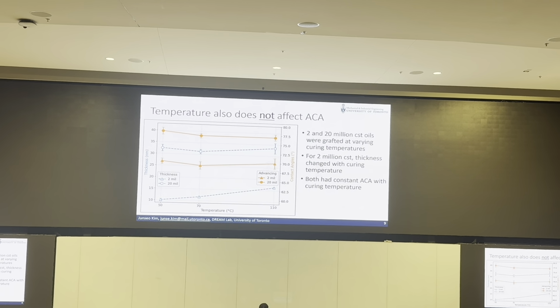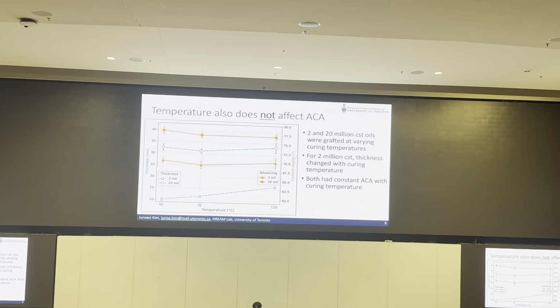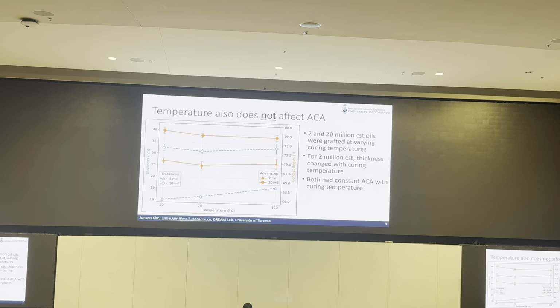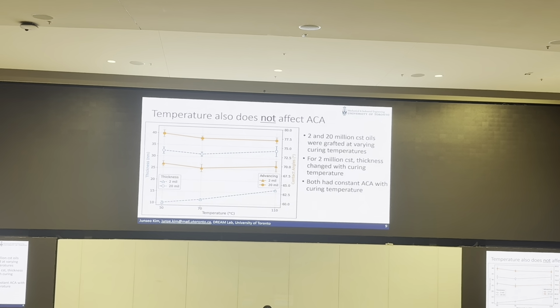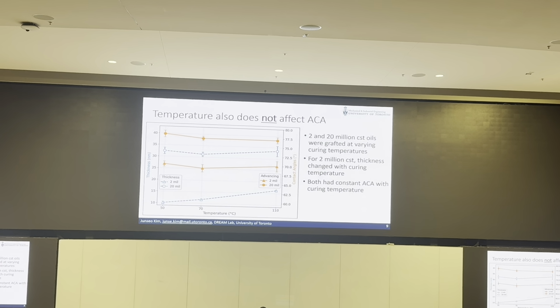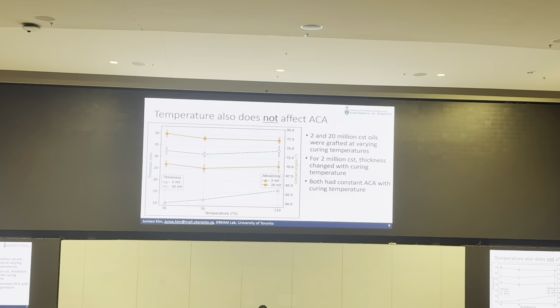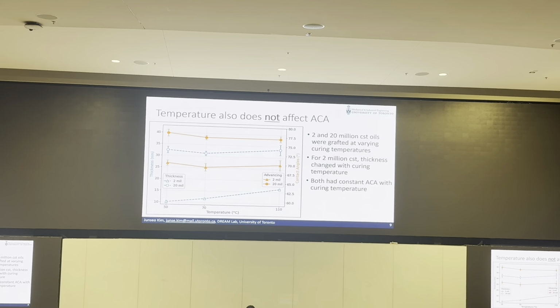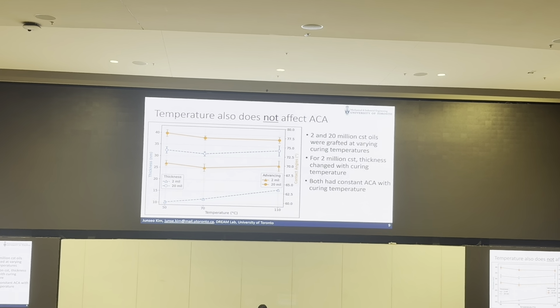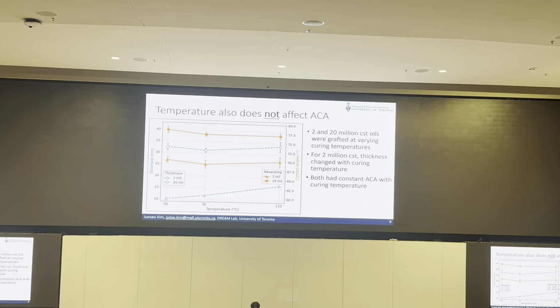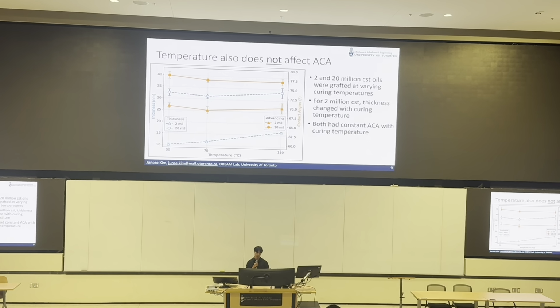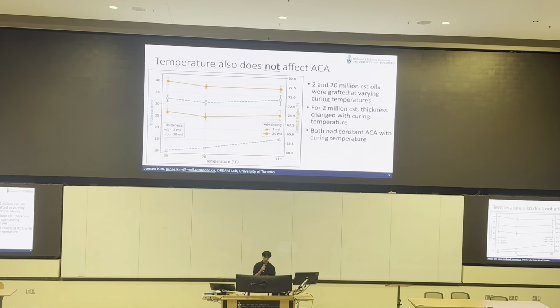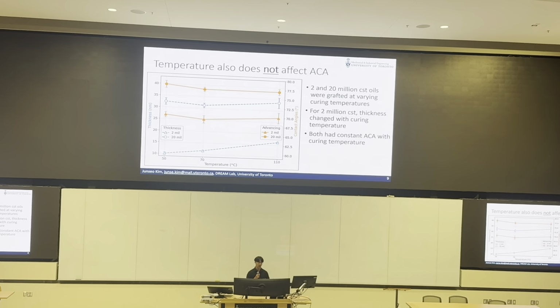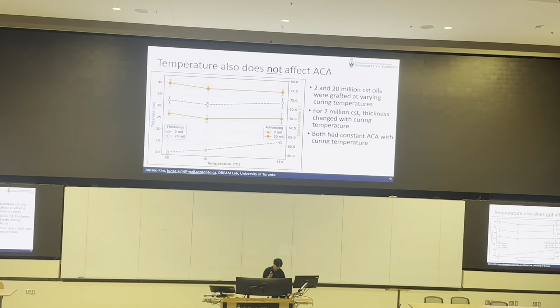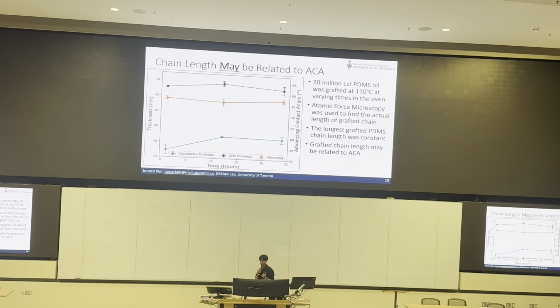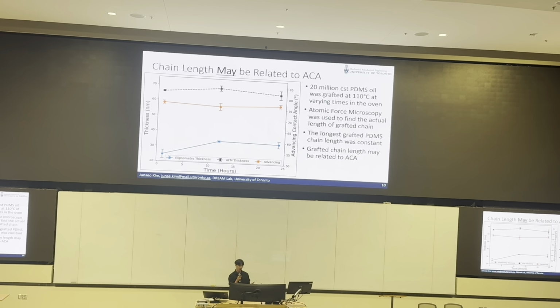This time I was using 2 million as well as 20 million centistokes PDMS, and they were grafted at varying curing temperatures. Similar plot, but temperature on the x-axis, and contact angle and thickness are dependent variables here. You can see that the blue line, which is the thickness, for the bottom one, that's the 2 million one. You can clearly see that there's an increase in thickness with curing temperature. However, for both the 2 million and 20 million, the advancing contact angle was very constant. So then what is related? What could be related is chain length, the chain length of what's grafted onto the surface.